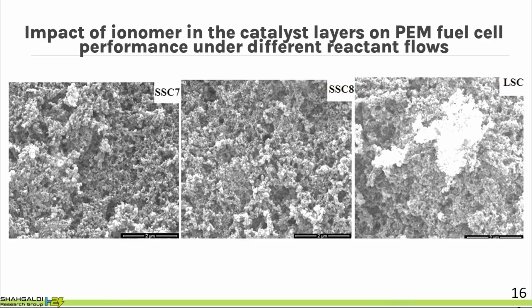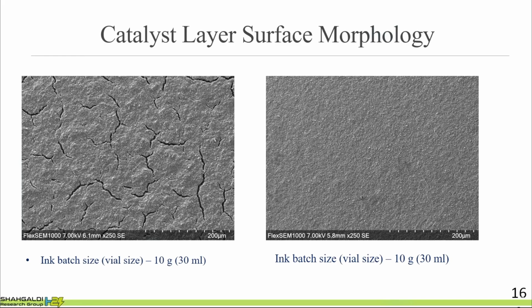Here it shows, for example, the images where we applied different kinds of ionomer. I show different SEM images where we applied shorter side chain ionomer and long side chain ionomer. You see that we end up with different porosity and agglomeration of the ionomer. And this image shows that we had the same catalyst, same ionomer, same method of mixing. The only thing that is different is the timing. And you see that when we coat the catalyst layer, we end up with a homogeneous layer on one side and another catalyst layer full of cracks. We don't need these cracks, because as soon as we start running our stack, the water goes through these cracks, making them wider and wider, and we have lamination of our catalyst layer. That is the reason that we need to pay attention to the mixing method as well.